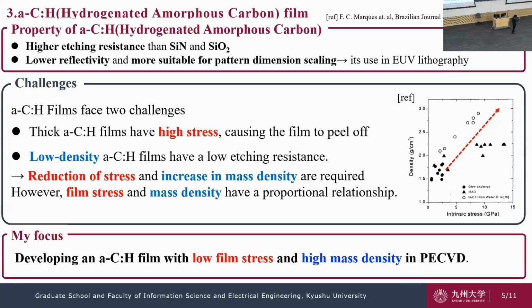So the ACH film is used in EUV lithography, but ACH film has two challenges. One problem is that thick ACH film has high film stress, causing the film to peel off and break down. One more problem is that low-density ACH film has low etching resistance. So reduction of stress and an increase in the mass density are required.